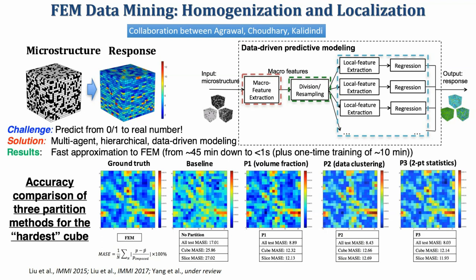So for a new microstructure, what it does is that it will take the 2-point statistics. It will find which of these clusters it belongs to, and then use the corresponding model. So it's like a hierarchical machine learning approach, where you are using different models and ultimately predicting the response at the voxel level. That's localization. You can also do it at the entire cube level, which is the homogenization, and that's also something that we have done, which is under review right now.